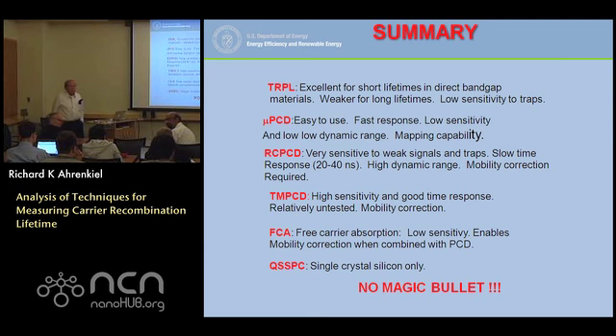Yes? If my understanding is correct, in a typical TRPL measurement, initially you inject very high intensity light into your sample. Well, I would start with the lowest intensity that was possible. Right. So my point is, initially you would have very high absorption near the surface. So you see an initial rapid decay of your TRPL. Well, that is true if the surface is not passivated.